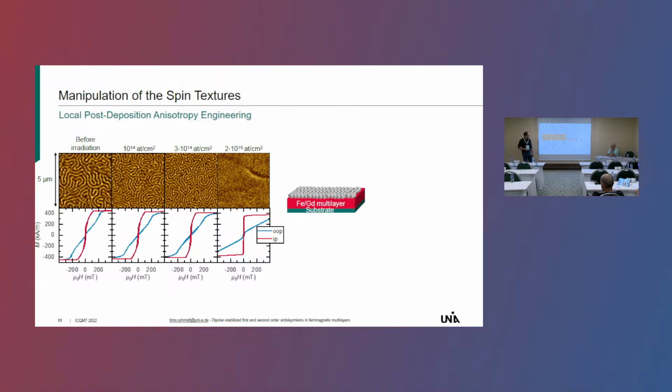And the next step would be to irradiate it with helium ions. And you can guess that the helium irradiation can't transfer through the nanospheres, so it only gets in between the nanospheres, and you only destroy the area where you don't have your nanospheres. And then if your nanospheres are approximately the size of your skyrmions, then you basically have a hole where these skyrmions can form in. And out of that hole, there are forbidden regions for them.